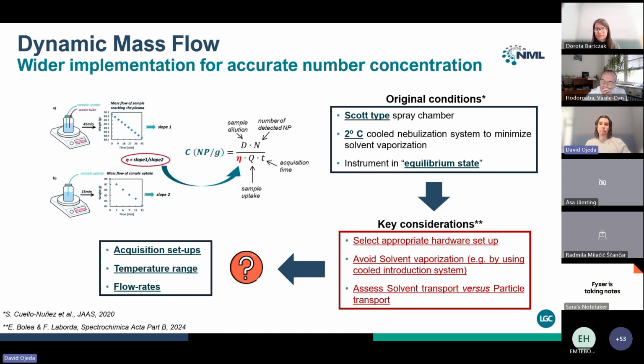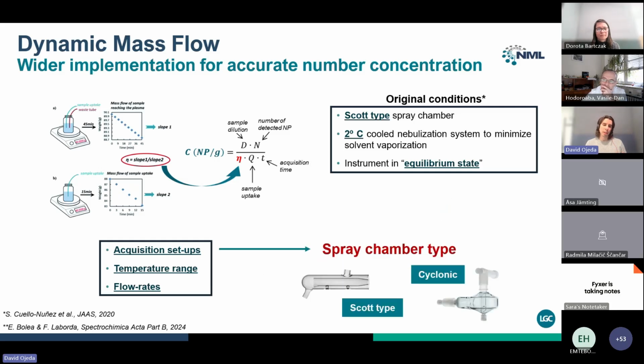Also, we need to avoid solvent vaporization, and that's why the temperature should be controlled. And we also need to assess that the solvent transport and the particle transport are the same for the determination of number concentration. To study these key considerations, we decided to use 2 different types of spray chambers to test the performance of the method with 2 different acquisition setups. On one hand, we have a Scott type spray chamber, and on the other hand, a cyclonic one.